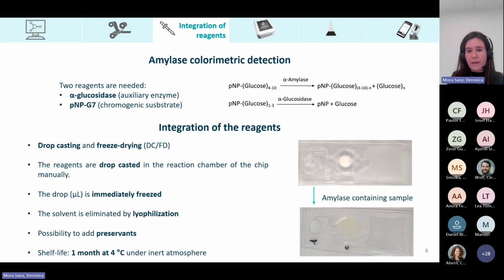By using this method, the shelf life of the chip is of 1 month at 4 degrees under inert atmosphere. Here we can see an image of the chip with the reagents in the reaction chamber. Then we add a solution containing amylase, and we can see how the reagents are dissolved, and the liquid turns yellow due to the formation of pNP.